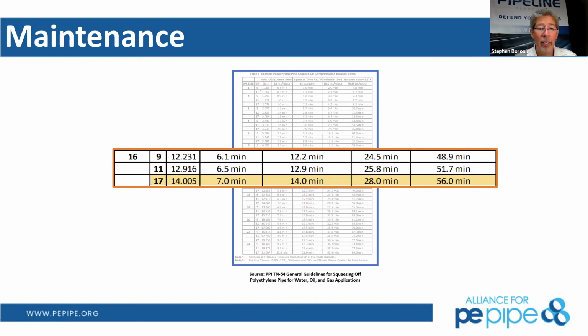In the guide, if you take a look at, I believe it's ASTM F1041, it will give you all of those ranges that you should be away. So as a rule of thumb, typically 3 ODs of the pipe that you're working with, minimum, away from any fitting or fusion joint that you might have in the system. You don't want to do a squeeze any closer than that, because then you risk possibly damaging that joint or that fitting that you may be close to.